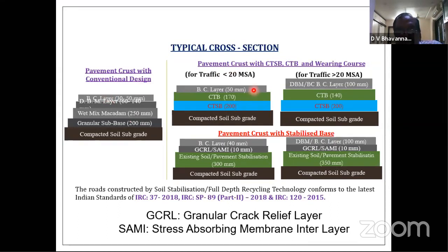Now, here two cases are there. One is with cement treated subbase and cement treated base, and another is using this chemical additive. You observe this up to traffic less than 20 MSA. Here, BC thickness is 50 mm, cement treated base is 170, and cement treated subbase 200. This is the compacted soil zone. Here, for traffic more than 20 MSA, it is one example, not a particular one. CTSB is 200, CT base is 140, and DBM and BC are put together 100 mm.